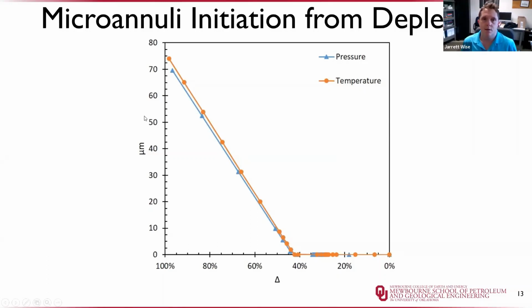So we see that the microannuli actually starts to form around approximately a 45% reduction in pressure from the mud weight. And we can see that it goes all the way down from like nanometer size all the way to roughly 80 microns.